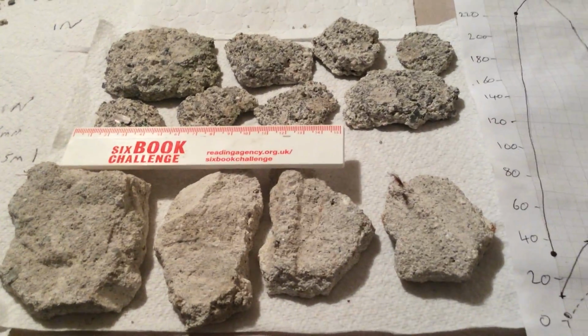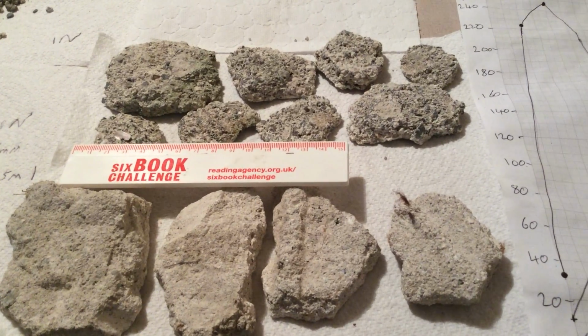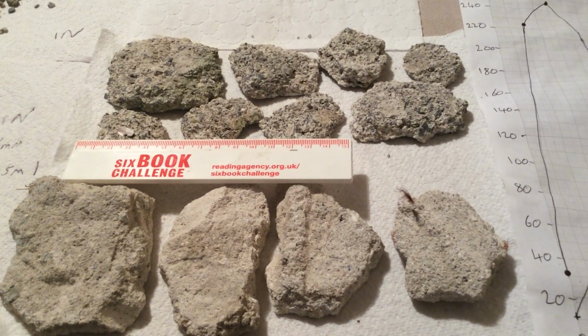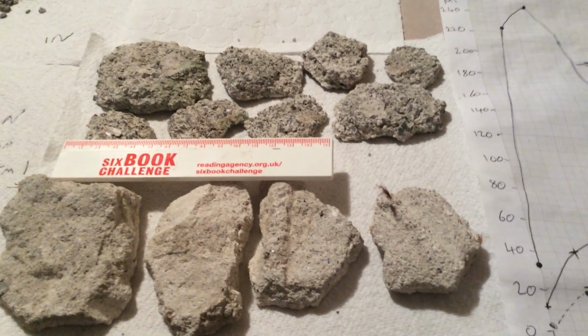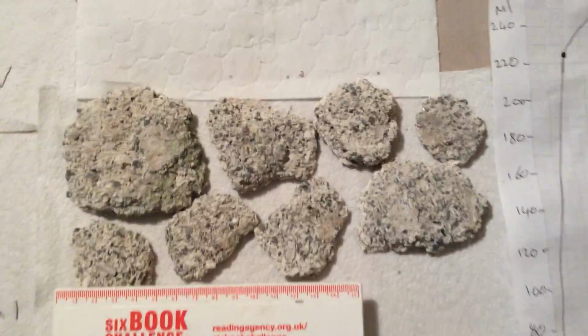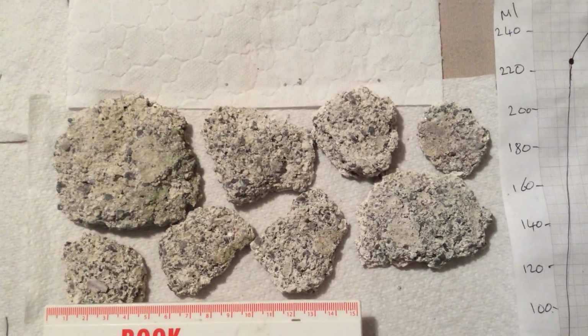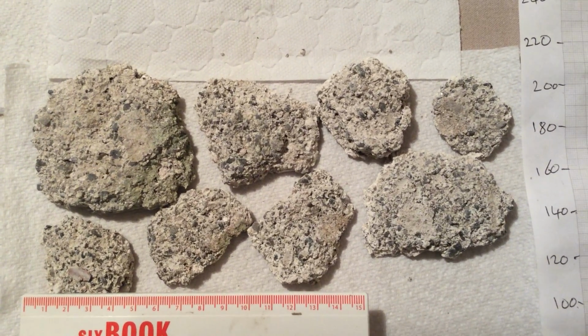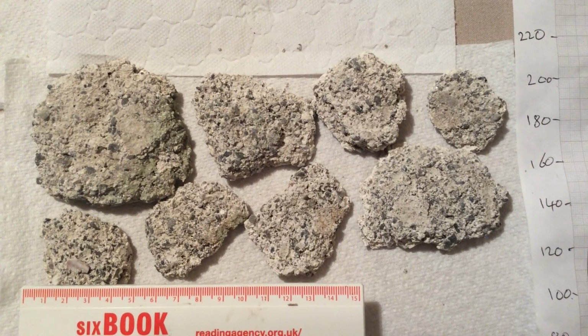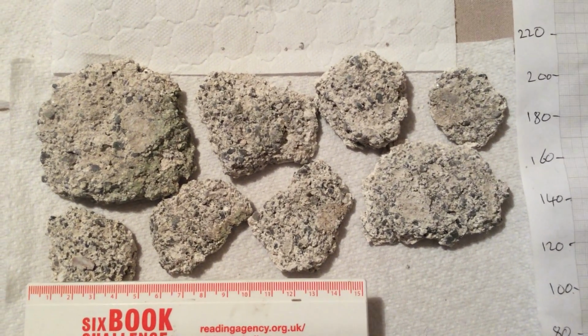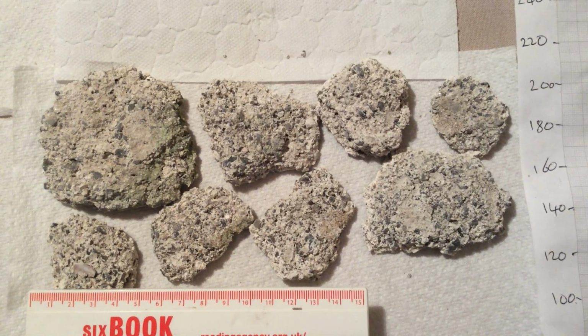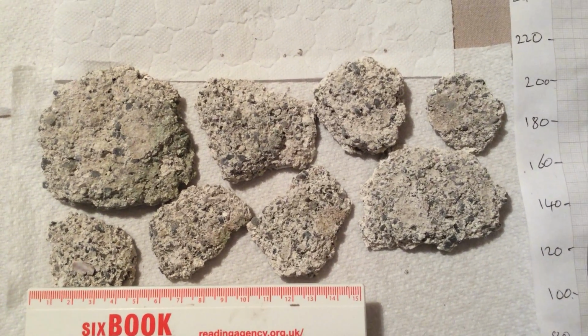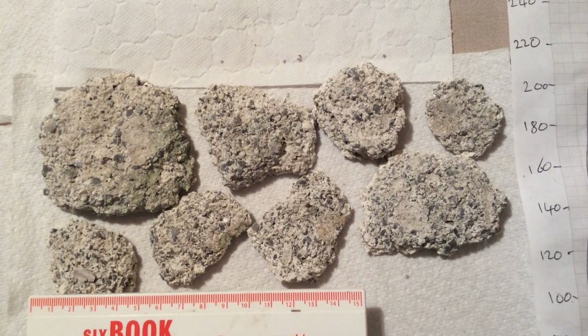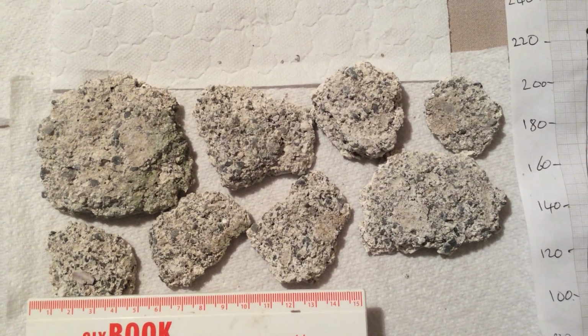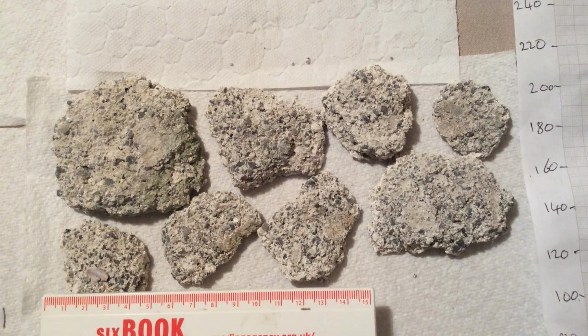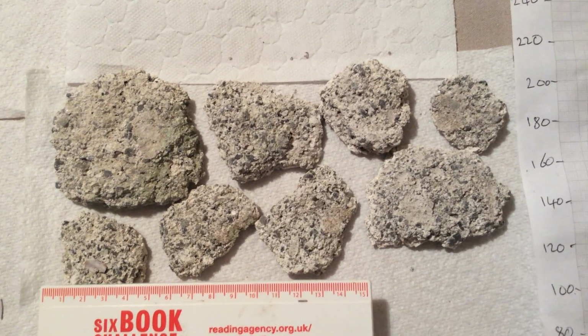What we have here are some samples taken from inside the building and outside the building. From outside the building, we see grey pebbles, about 2 or 3 centimeters mostly in size, and lime as well. And when we dissolve it away, it turns out 50% of the volume of the material is lime, which disappears. So a very high lime concentration.